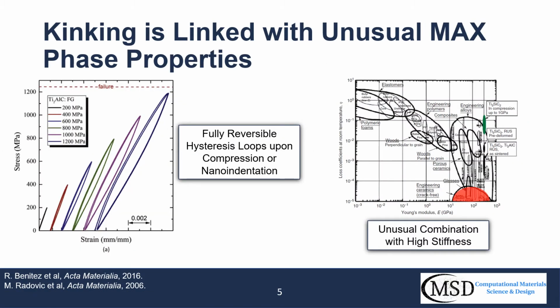I'll briefly touch on perhaps the most intriguing MAX phase property associated with kinking, and this is their ability to dissipate large amounts of mechanical energy. When compressed or indented up to gigapascal stresses, they form fully reversible hysteresis loops. Combined with their high stiffness, this is a very unusual combination indeed, as most engineering ceramics typically only possess the high stiffness. So it's our hope that a better understanding of the kinking mechanism should allow us to take advantage of this unique MAX phase behavior, among others as well.